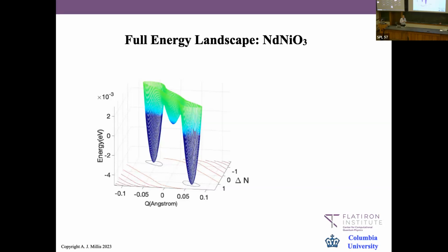otherwise the whole scheme breaks down and you have to start over, basically. So when you're saying that it's mixed, this 0.05 is about half of what in principle is possible with Q — or a third, something like that. But to me the mix really, just to repeat myself: there is not even a metastable minimum if I set delta n equals 0 and scan in Q. There is not even a metastable minimum if I set Q equals 0 and scan in delta n. That's what it really means to me.